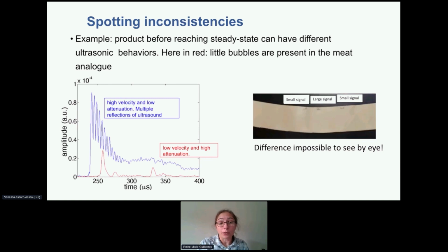Another possible application of that is to spot inconsistencies in your material. Here I'm showing just a short example. In blue, you have a signal that we get with a regular extrudate in the lab with the formulation I showed before. And you can see that it has a lot of peaks and the signal is pretty large. But sometimes what you get is something like the red curve. It has a much lower velocity and a much higher attenuation. So what it means is that the material is different.